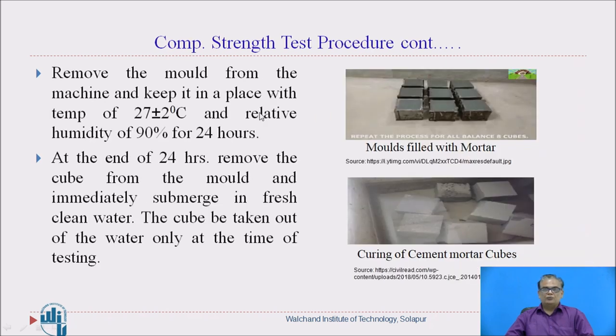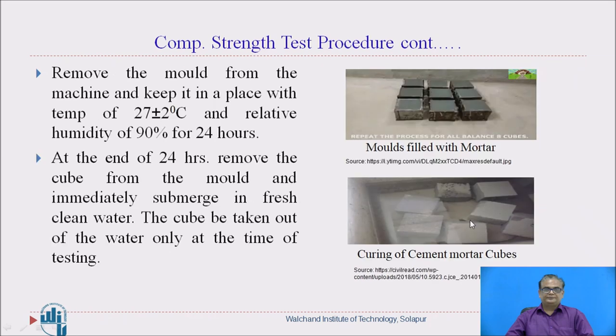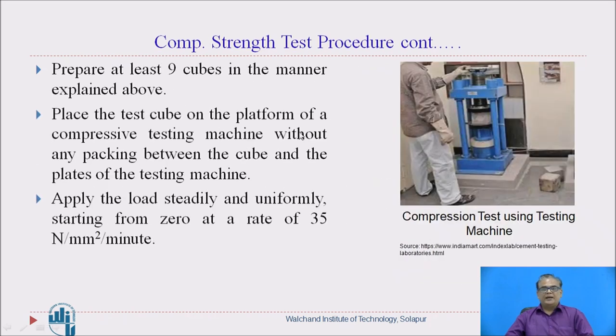The cube molds are removed from the machine and kept at 27 ± 2°C and relative humidity of 90% for 24 hours. After 24 hours, the cubes are removed from the mold and immersed in water for curing, as shown. At least 9 cubes are prepared. Three cubes are tested at 3 days, three at 7 days, and three at 28 days according to the Indian Standard code on a compression testing machine.